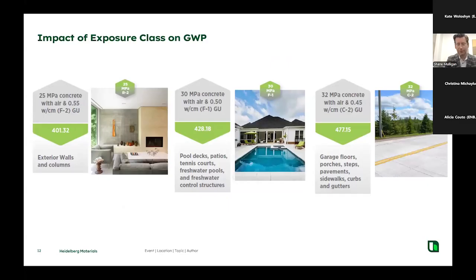Exposure class is another important consideration. As concrete is exposed to more and more aggressive environments, whether it's chloride penetration, sulfates in the soil, road salting, whatever the case might be, the concrete matrix needs to be denser to help stand up to that attack. And so as you get more aggressive exposure classes, you get more dense concretes, which generally has the effect of increasing your carbon intensity because you're using more cementitious content to hit those higher densities.